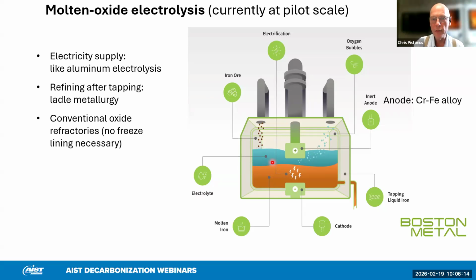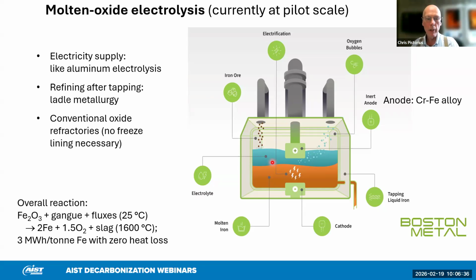And the refractory for this vessel will take normal refractories, because one can tweak the slag to both balance the electricity conduction through it, as well as the compatibility between the slag and the refractory. If you add up all the numbers with no heat losses, the total is around 3 megawatt hours per ton. So it makes sense that the total will be around 3.